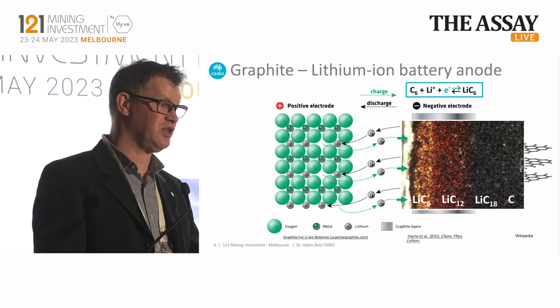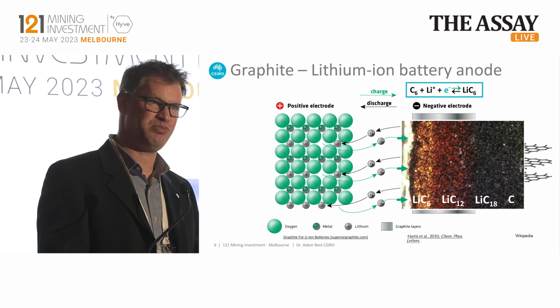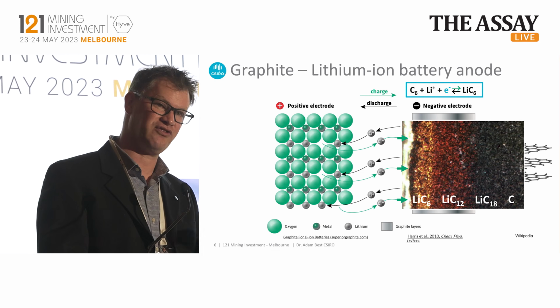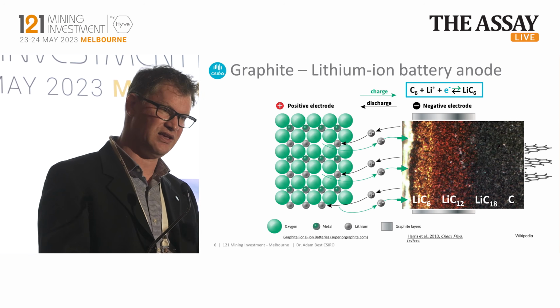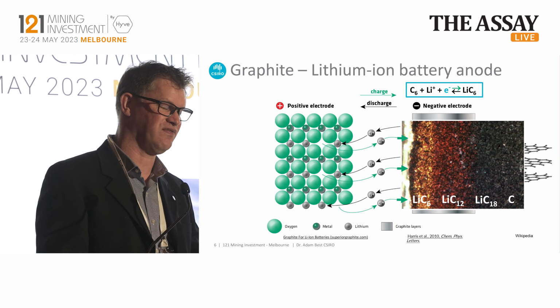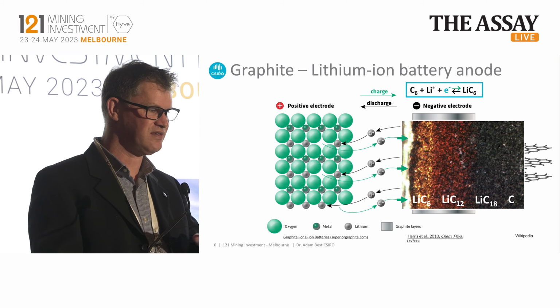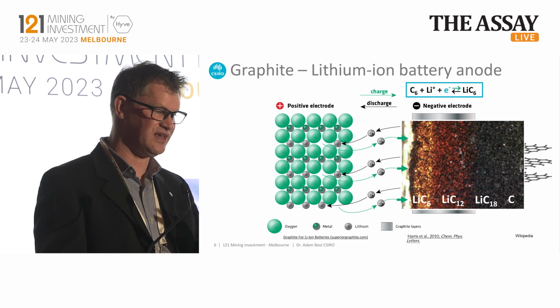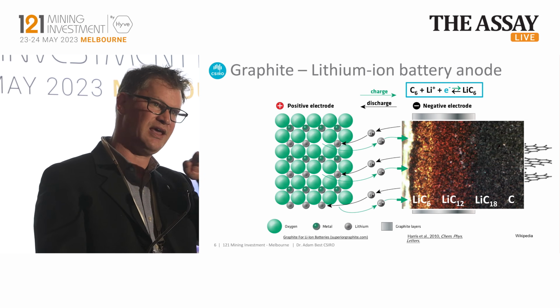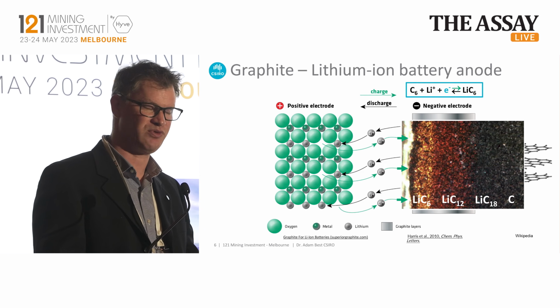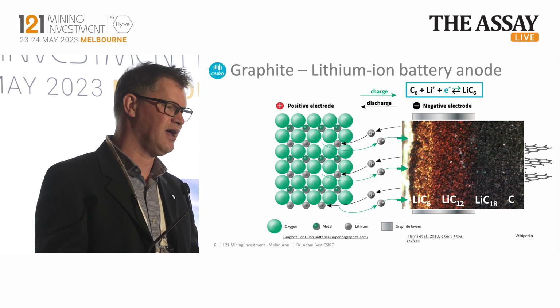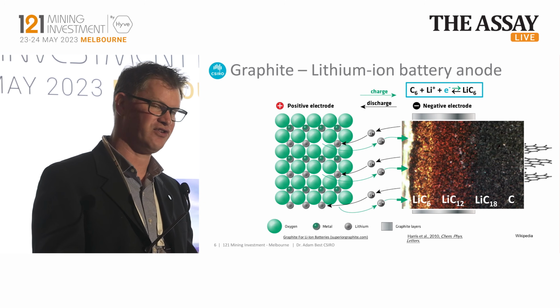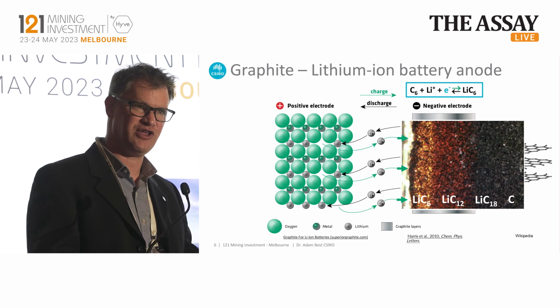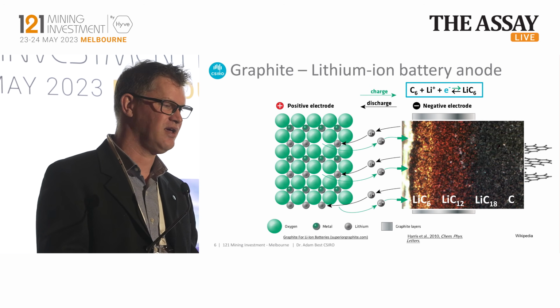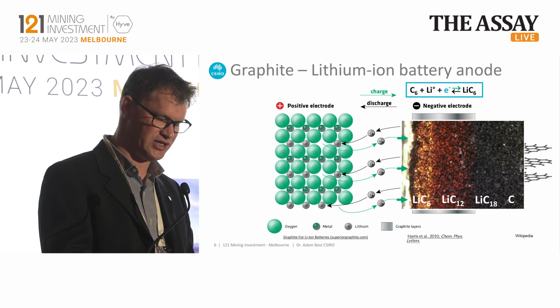If you go into what we call an overcharge regime, i.e. we put the battery into an abuse condition, the actual electrode actually looks silver, and that's because you've actually got lithium plated to the surface of that material. So these charge-discharge steps, these colors also correspond to steps in the discharge profile or the charging profile of graphite that we as researchers can see and track and follow as to the state of charge of these electrodes. But more importantly, battery management systems can use those to track the state of health and the state of charge of batteries.